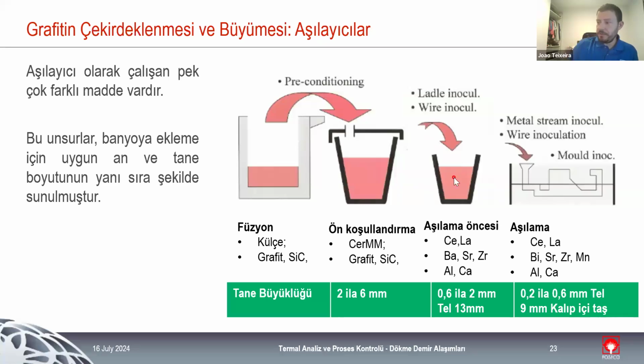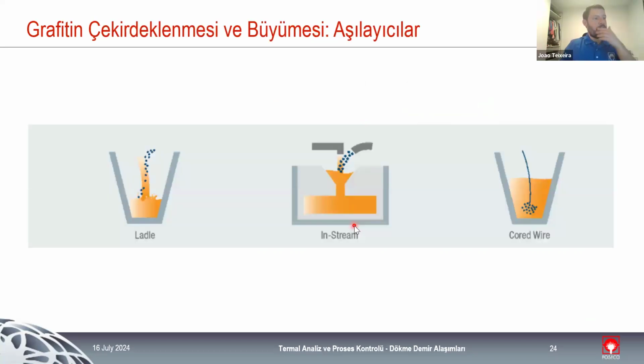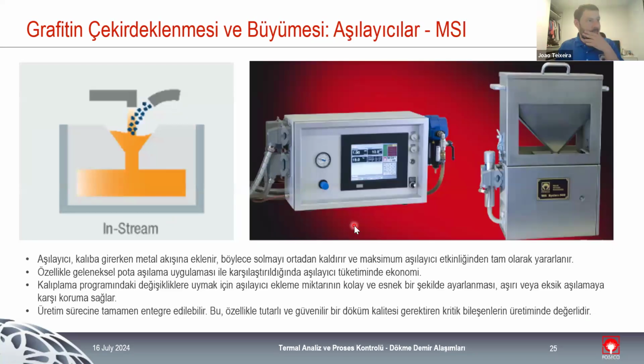And we can see the different elements that we are going to have in the different stages of inoculation. Again, ladle, in-stream, or core wire. For example, for in-stream, we have the MSI unit. Normally, in-stream is really popular, especially for the automotive industry, for the production of smaller casts, where we really need a lot of speed and a lot of production capacity. And it is an easy system for us to have a high replicability of the process. So we are always having the same amount of inoculant. So we can compare one cast with another on the basis of the inoculation, because we are always having the same amount based on the amount of metal that we are pouring to the mold.